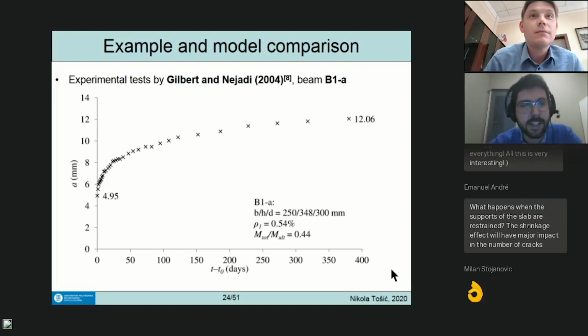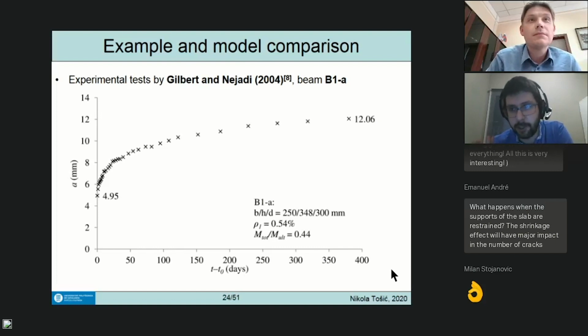Okay, I'm okay, sorry. So these are the deflections that were measured for 380 days, starting from 14 until 394. So it was under load for 380 days, and it went from 5 millimeters to 12.06. So a 2.4 times increase of the deflection over time.